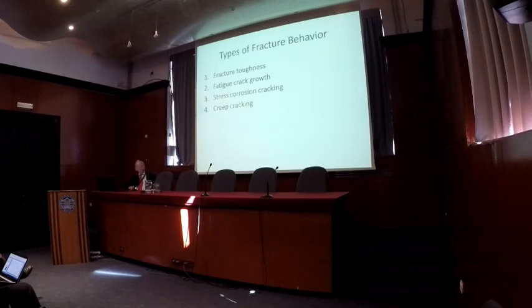Here are the kind of behaviors that we have looked at in fracture mechanics. Fracture toughness, which is failure under a rising or a monotonic load. Fatigue crack growth, which is failure under cyclic or repeated loading. And stress corrosion cracking, which is often called environmentally enhanced cracking, which represents then a load, a crack, and a bad environment. Not in linear elastic approaches, but in nonlinear approaches, we sometimes talk creep cracking.